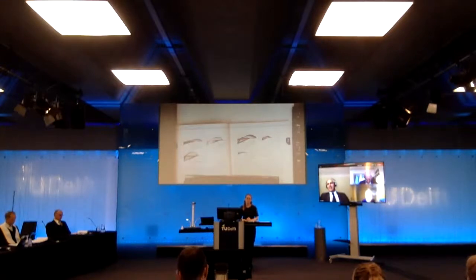So let me go then to a physical aspect, which I don't know if you have thought about. You know that if you go to the nanoscale, nanocrystals have lower melting temperature. There are a lot of issues about the surface melting, and for instance, it evaporates at 200 degrees Celsius. It's unbelievable, while the bulk evaporation temperature is something like 900 degrees. Just to give an example,